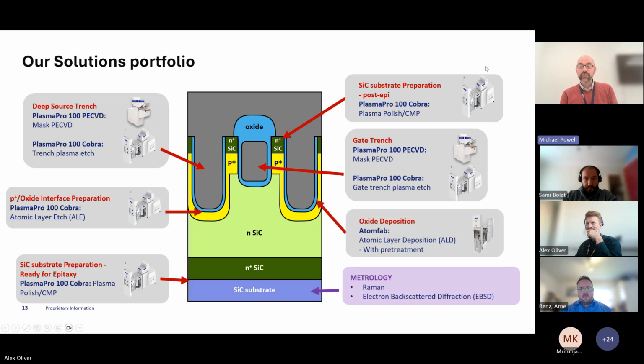Thank you very much. If you go through to our silicon carbide market, where we can show how our technologies can interface with this, we have a wide range of different technologies that we can leverage to improve the quality of a silicon carbide device. It's everything from the initial silicon carbide layer right at the bottom, where we have a plasma polish process, which means that rather than having to use the CMP process, you can use a plasma process to get the same kind of control on the surface, all the way through to the gate oxide deposition.